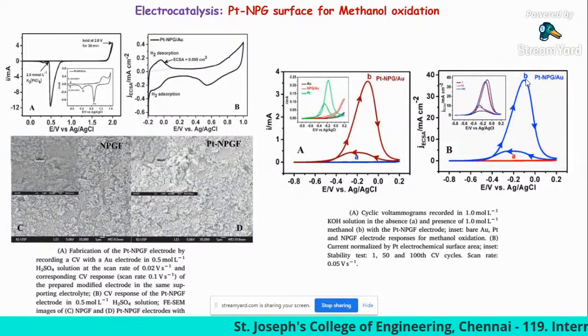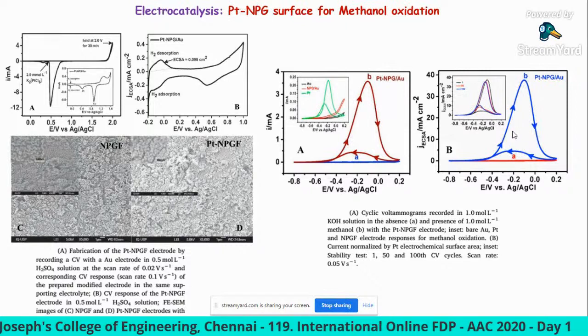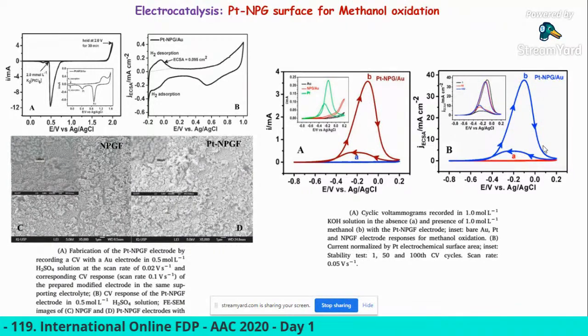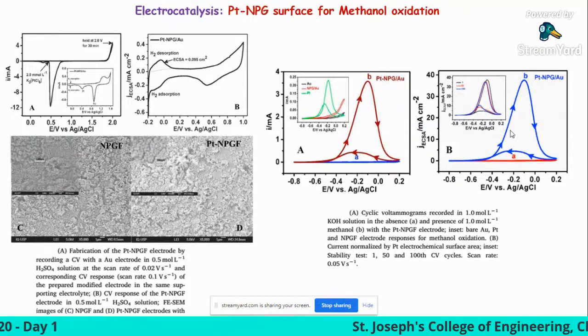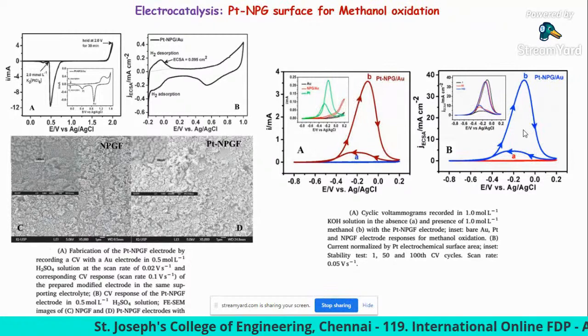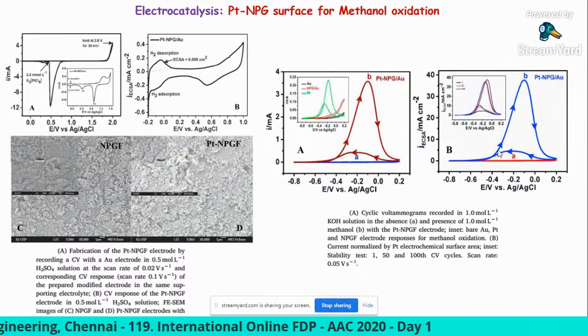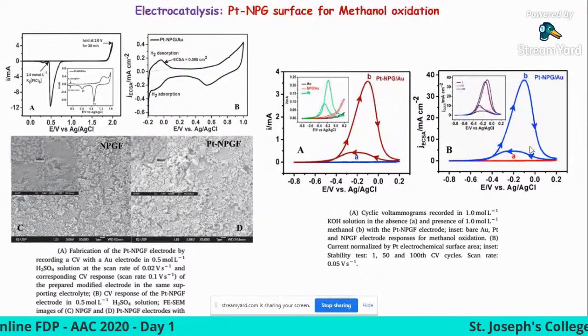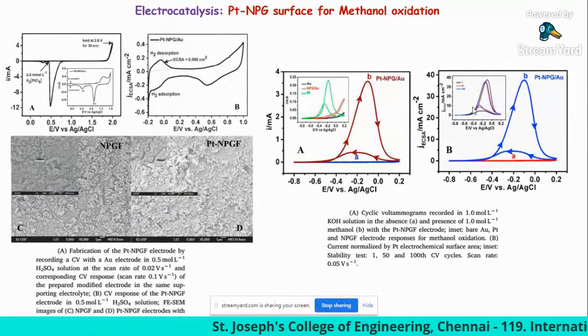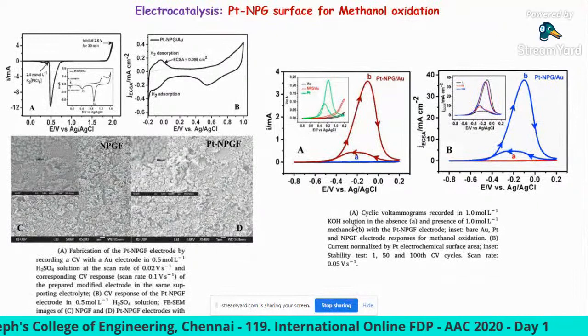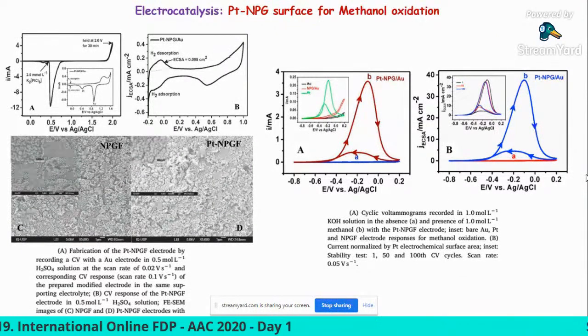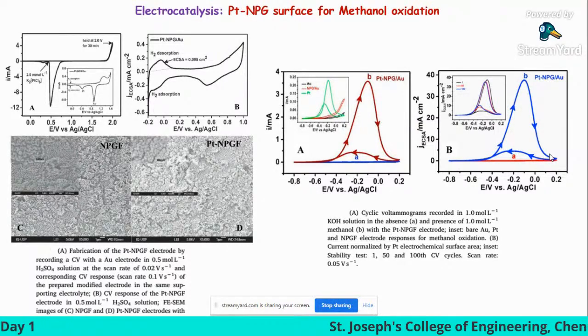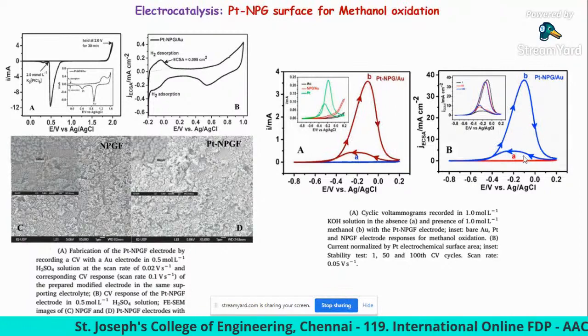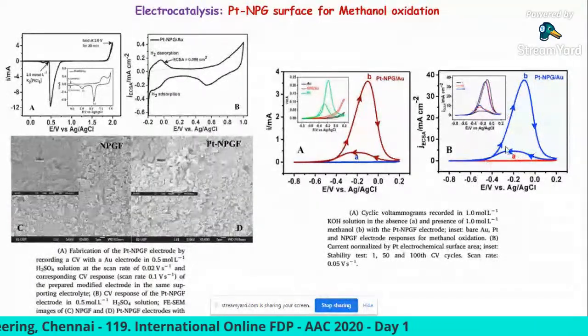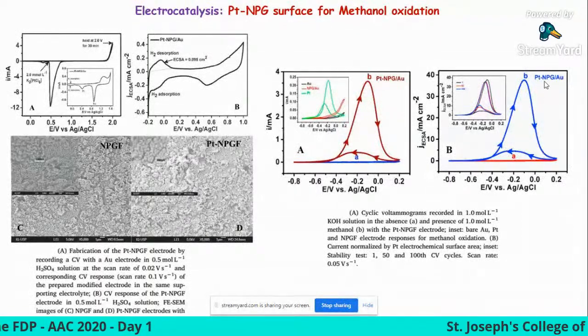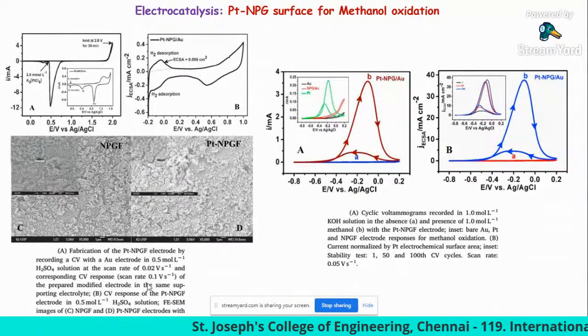Also, one interesting thing is the electrode fouling, because during methanol oxidation, carbon monoxide is formed as a byproduct, which adsorbs on the Pt surface and inhibits the performance of the catalyst. That is one of the big problems in methanol oxidation reaction. However, in this case, the generated carbon monoxide is not inhibiting the Pt surface, because this experiment was performed in potassium hydroxide solution. So the hydroxide ions chemisorb on the nanoporous gold surface, which further oxidizes the carbon monoxide, and thereby inhibits the fouling of the Pt surface. Because nanoporous gold is also a good catalyst for the carbon monoxide oxidation reaction.